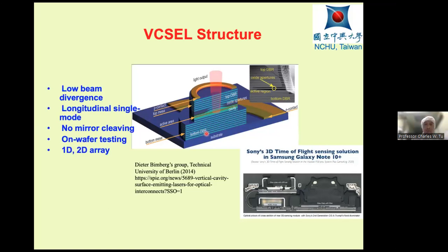But here with the VCSEL, the vertical cavity has the advantages of lower beam divergence, it can be a circular beam instead of elliptical. And then it has a longitudinal single mode because the cavity is very short, and no mirror cleaving, because we rely on the bottom and the top mirror. And these mirrors were grown epitaxially, by gallium arsenide, aluminum arsenide, a so-called distributed Bragg reflector.